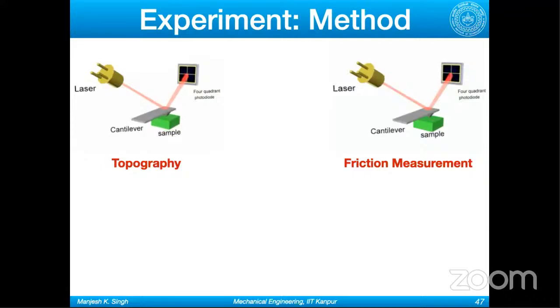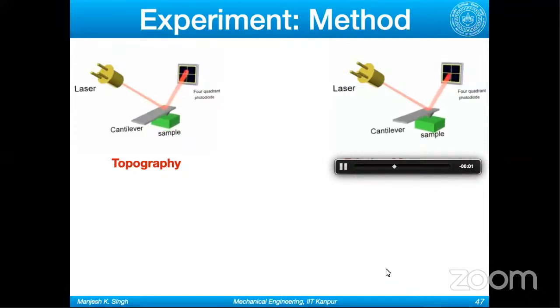As I was saying, we use AFM-based colloidal probe lateral force microscopy. Normally we use AFM to get the topology of the surface by tapping mode or different modes, because when you do the rastering of the surface, because of the surface profile, your cantilever will move up and down, and you can get the profile of the surface. But you can also measure the friction using AFM. You have four diode quadrants. Whenever the cantilever faces a lateral force, it will twist and move on the diode in the XY direction. And from there, if you calibrate your cantilever in the lateral direction as well for lateral stiffness and sensitivity, you can measure the lateral force or friction force, so to say.